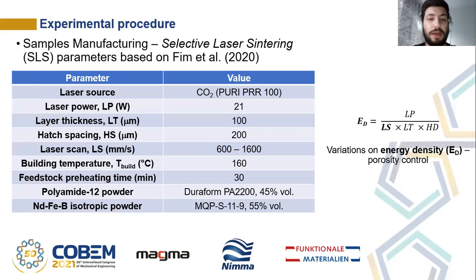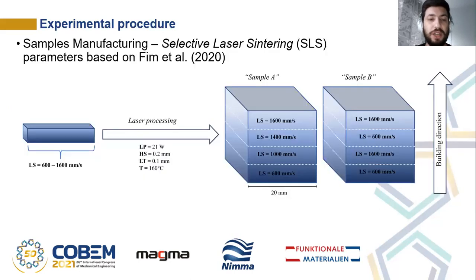In this way, magnetic samples were obtained via selective laser sintering processing, following parameters described by Fim and co-authors as listed in the table. The laser scan speed was the only variable processing parameter, ranging from 600 to 1600 millimeters per second. A feedstock composed of 45% in volume of polyamide and 55% in volume of neodymium-iron-boron isotropic powder was used. In this investigation, cubic samples with dimensions of 20 by 20 by 20 millimeters each were obtained via selective laser sintering following two different approaches. In the first one, called sample A, the design consisted of printing samples varying the laser scan speed in the building direction.